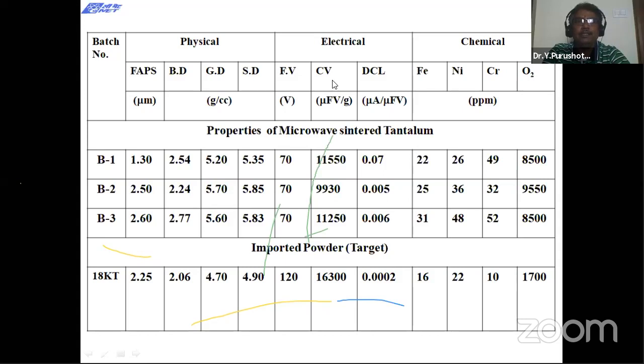Our electrical, physical and chemical properties are less compared to imported powder, because we did the entire experiments under inert atmosphere. Due to that, oxygen pickup was more compared to imported powder. So this is because of this oxygen. DC leakage was more, and capacitance CV is more. Due to that, we could not get the desired properties as per our requirements by microwave sintering, but we are able to sinter the materials.